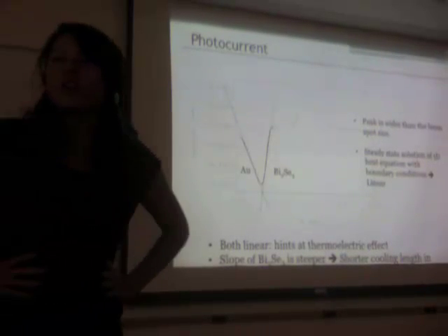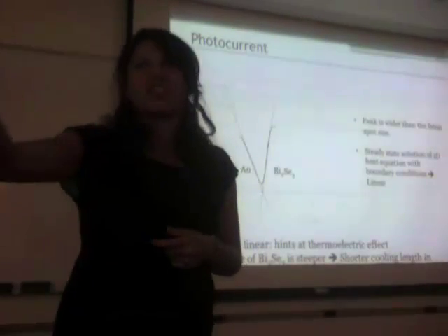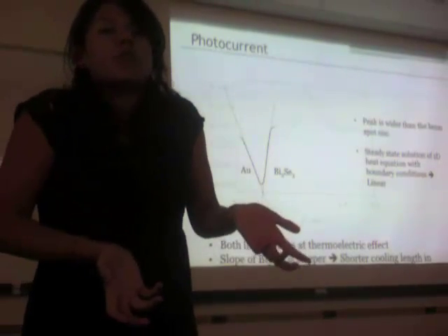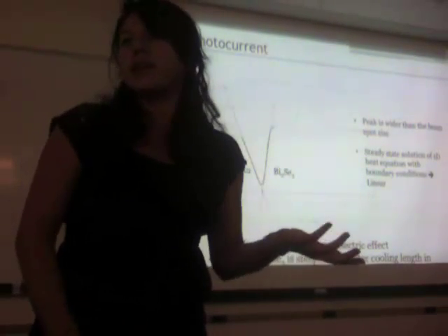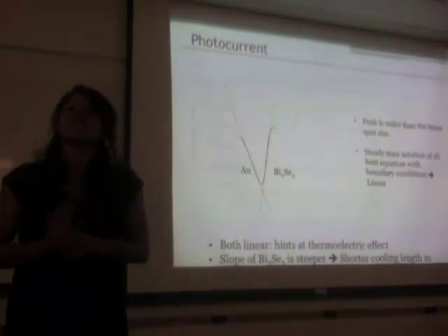Is there any expectation of what the behavior will be, or is this absolutely pioneering? We went into this without expectations, because you can trick your brain into seeing things, especially if you want to see a photothermoelectric effect. But it's not too far of a reach to say that there is photocurrent generation due to the photothermoelectric effect, because bismuth selenide at the surface is a graphene lookalike. And since in graphene you see this effect, it's not too far of a stretch to think that. But we went into it not really expecting it.